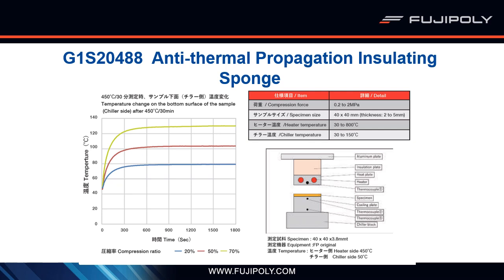So you can see once we get up to 50% compression, we're a little bit over 100 C. And then once you really start to compress this material down, about 70%, which is really the maximum compression that this material will bottom out at, you can see we're somewhere about 130 degrees Celsius. So still a pretty good thermal resistance between the hot side and the cold side, even at some of the higher percent compression. So it's doing a fairly good job of really keeping that heat down. 450 C is a fairly high temperature. When you talk about battery failure, you may not be reaching quite up there, but it still gives you a good leeway, good space between actually going into thermal runaway.